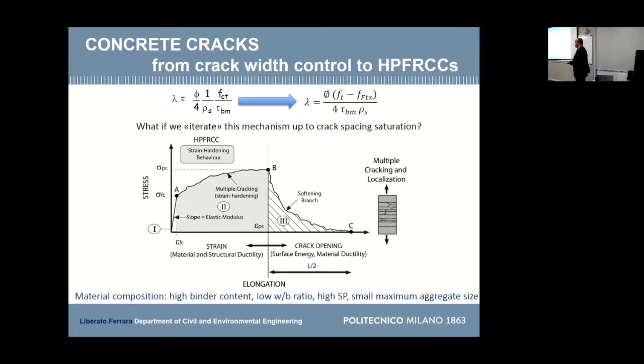If you would have ordinary concrete after this point, your stress would immediately soften. You have high performance concrete, you have fibers inside. So what do the fibers do? They pick up the stress from a crack and redistribute it to the neighboring cross sections, and you can form another crack, and you can form another crack.